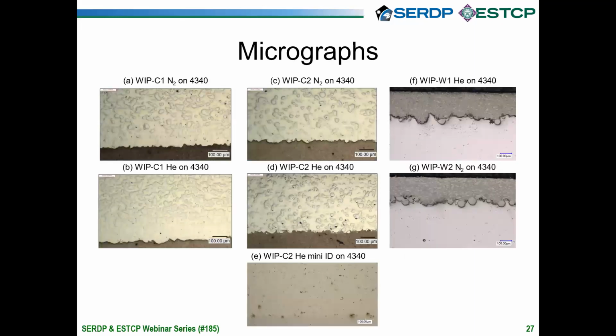All right, so at this time, I will go into some of the key test results that we found on the project. The first is micrographs. So what we were looking for with micrographs is a dense coating with minimal porosity. What we found is that all of our coatings met that criteria.